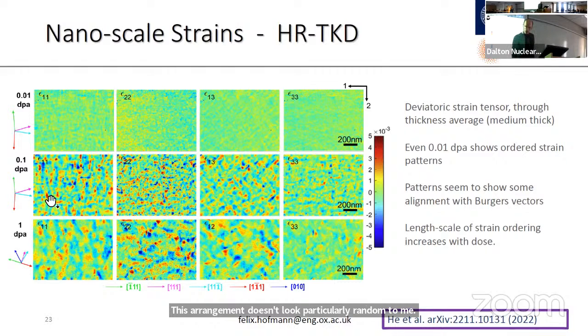As you then go to higher doses, this organization of defects becomes more and more pronounced, and the organization of strain fields becomes more and more pronounced. You can also see that the length scale of this organization keeps increasing with increasing dose, and actually becomes much greater than the length scale associated with collision cascades. So there's clearly collaborative self-organization of defects in this material.